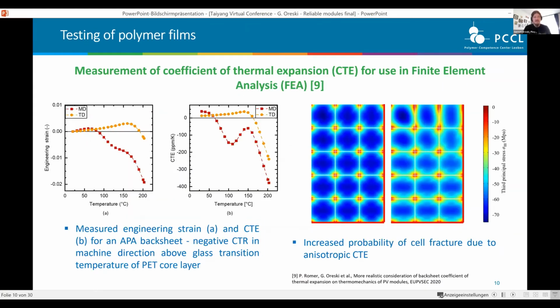Another thing is that you can measure certain properties and use them for further analysis and modeling. That's an example we presented this year at the PVSec. We measured the coefficient of thermal expansion for different backsheets. And as with most polymers, we have anisotropic properties there. When we increase the temperature, sometimes we also have negative thermal expansion coefficients. That means shrinkage. And our colleague from Fraunhofer ISE, Pascal Romer, then used these values for finite element analysis and found that, because of these anisotropic properties, we have an increased probability of cell fracture during lamination.